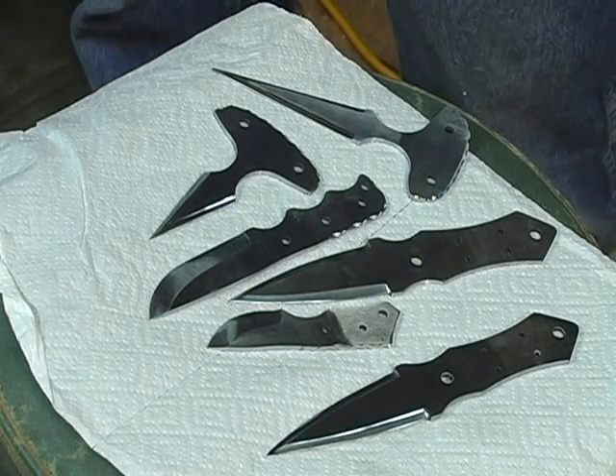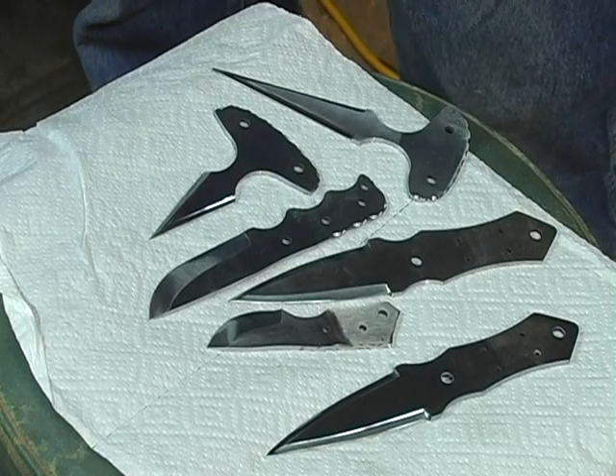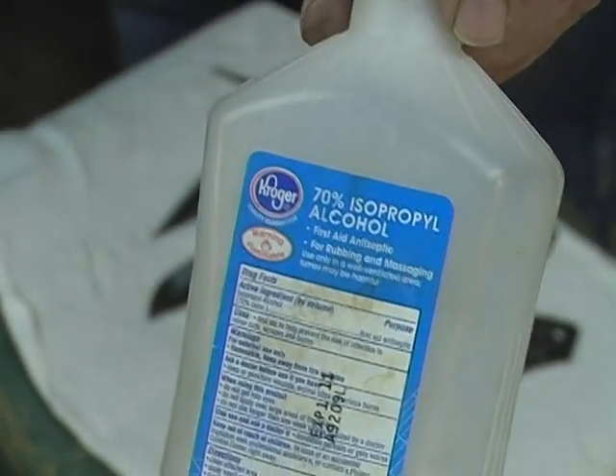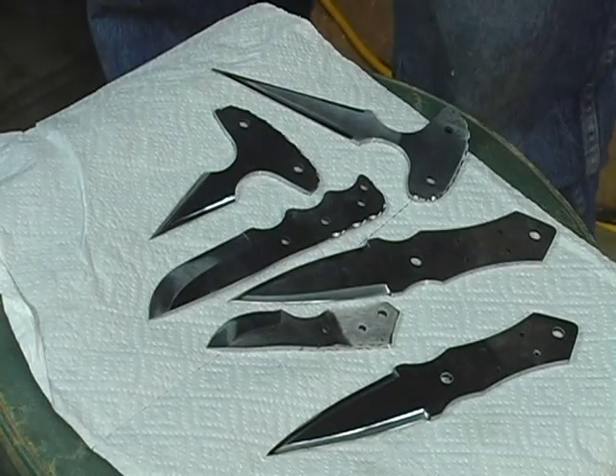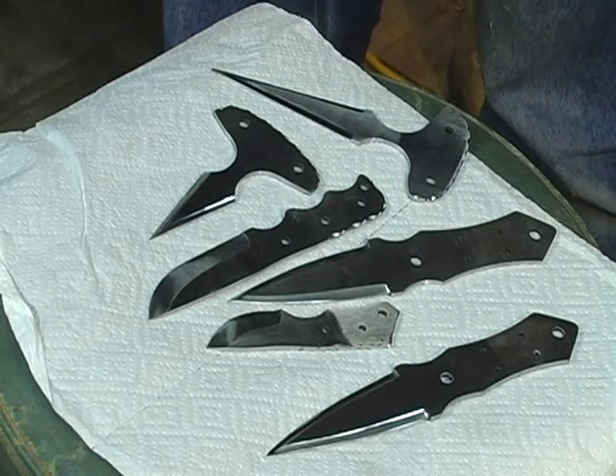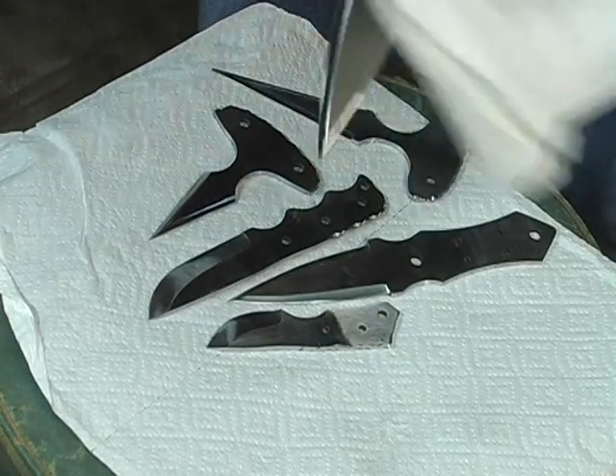What we're going to do is just clean up the blades a little bit, make sure there's no oil or grease on them. One thing you want to do is make sure your blades are clean before you etch them — if there's any oil or grease on the blade, that part won't etch. So all I'm going to use is just common rubbing alcohol. It will remove any oil or grease and not leave any residue. Just give them a quick wipe down with that.